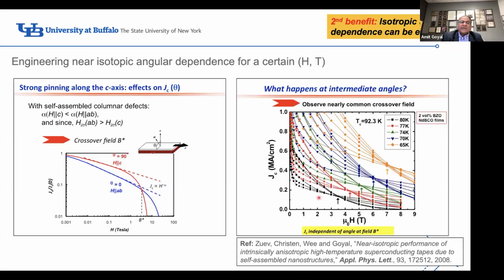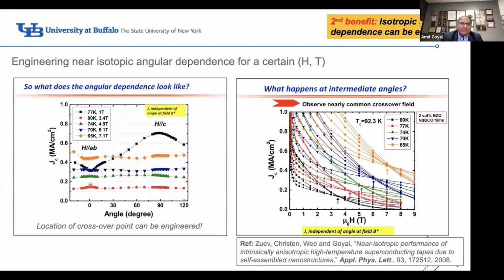Now, it turns out that if you pass a current at any other angle, it also goes through here, which means that at any of these points, you get an isotropic dependence, meaning if this is a crossover point, at this point, 74 Kelvin and 4.9 Tesla, we have the same current carrying ability irrespective of the magnetic field orientation.